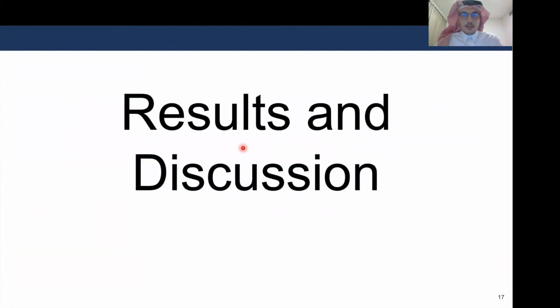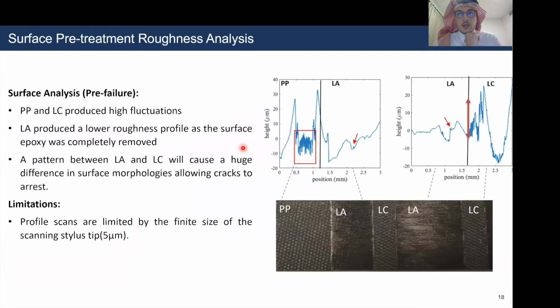So for the results and the discussion, let us start with results before mechanically testing those T-joints, or before the tension happens. Sorry. So the skin, just to illustrate the impact of the different pre-treatment techniques I applied, was treated with a peel ply, LA and LC, and surface profile morphologies were analyzed using a surface profilometer.